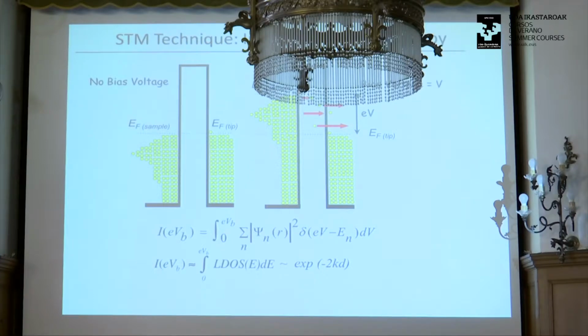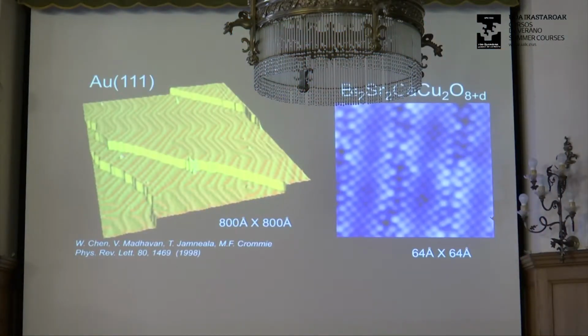But the one important thing in STM that you have to realize, which will be important for my lecture tomorrow, is that in STM, we just don't measure the number of states from here to here. Each state is weighted by the square of the wave function, okay? And this is going to be really important when we do quasi-particle interference. So because the STM is sensitive to the square of the wave function, the wave functions die exponentially into space. So the distance between the tip and the sample basically controls the tunnel current. And because of that, we're able to take very high resolution, atomic resolution images, because the tunnel current depends sensitively on the distance between the tip and the sample.